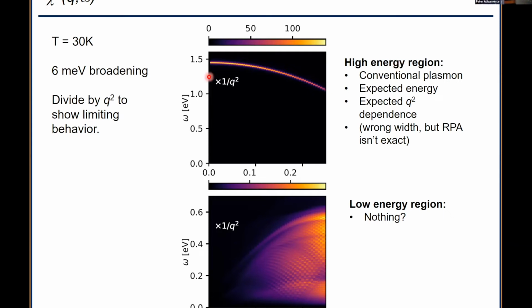In the RPA, using no adjustable parameters at all, by the way. All that's used are the known band dispersions and the known background dielectric constant, which I think is 2.5 or so, I forget exactly. And you just execute the calculation. The first thing you see is there's a plasmon, and it sits at an energy that's not too far away from the experimentally observed one. The key difference is it's extremely sharp in RPA, whereas in the experiment, it's broader by 2 or 3 orders of magnitude.